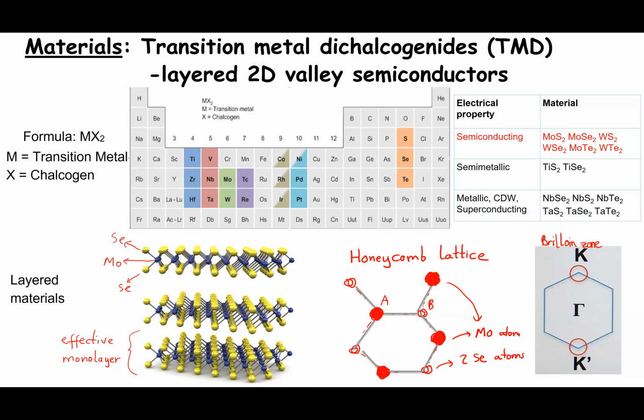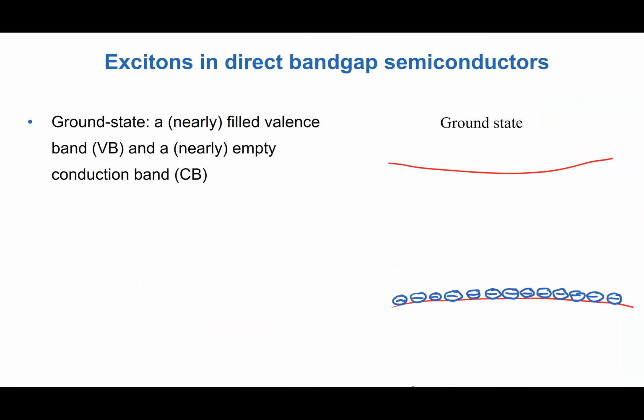This indeed is the case for monolayer TMDs. Because A and B sites are very different, this inversion symmetry is broken, and we expect a gapped material, and that's why we have massive conduction and valence band systems. Okay, so now you can think of this as a conduction band, this as a valence band.